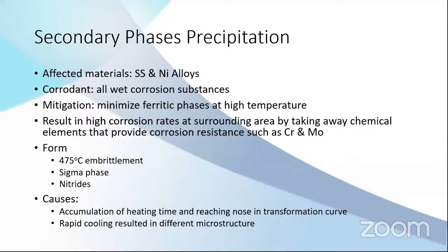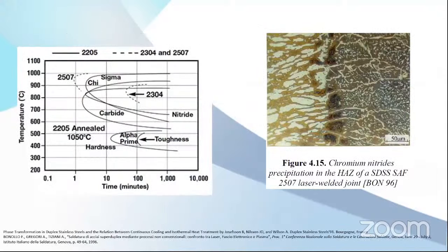And with this secondary phase, not only high temperature but also rapid cooling can cause this, especially with stainless steel or alloys that have nitrides. When it gets cooled very quickly, the nitrides react with the chromium normally, and then you can get chromium nitrides. So the cooling rate must be balanced, not too fast and not too slow. This is an example. This is the same, a nose, similar to the sensitization by chromium carbide before.